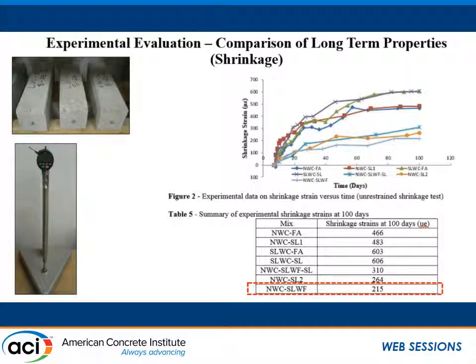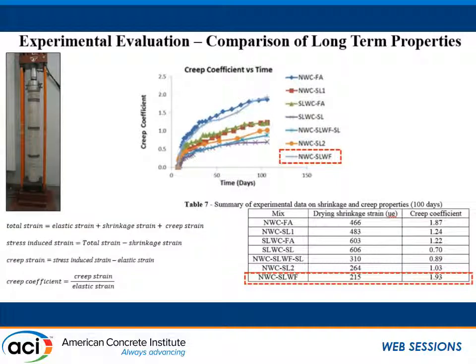This slide shows the development of the drying shrinkage strains for all seven deck mixes with time. The mix that developed the lowest drying shrinkage strain was the mix with normal weight coarse aggregates and saturated lightweight fine aggregates. It had a drying shrinkage strain at 100 days equal to 215 microstrain. The same comparison was done for creep properties using the creep coefficient, which is the metric used in the age-adjusted effective modulus method. In this study, the very same mix that exhibited the lowest drying shrinkage also exhibited the highest creep. However, it may not always be possible to find a mix with both low shrinkage and high creep. In those cases, priority should be given to a mix with low shrinkage, because it is the free shrinkage of the deck that serves as the catalyst for creating those tensile stresses.